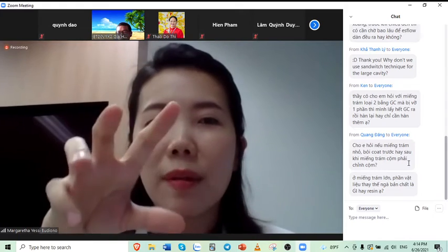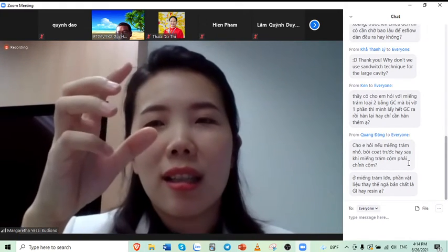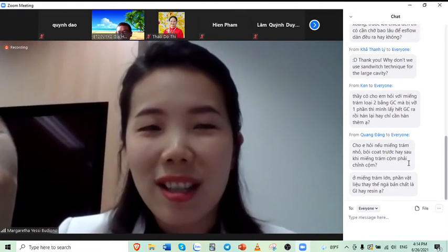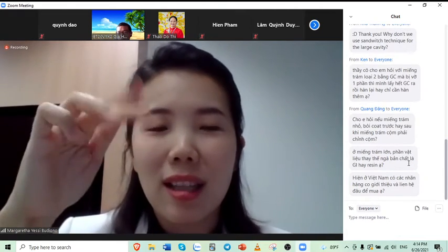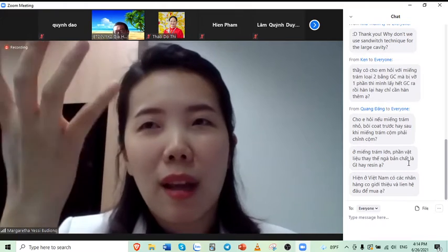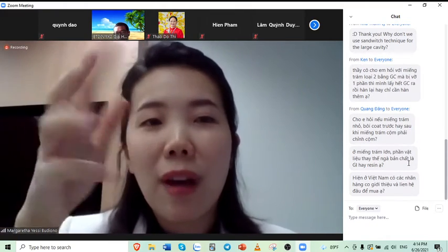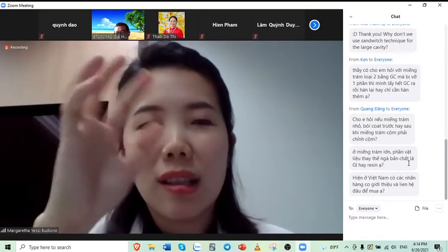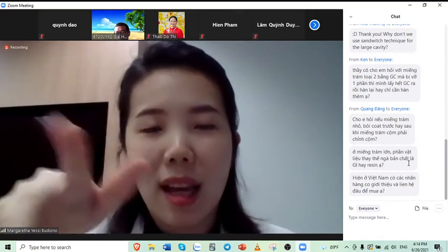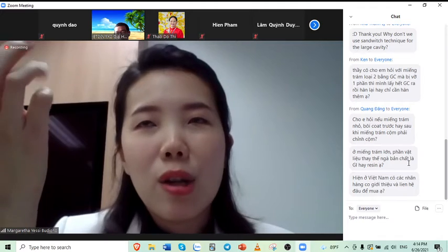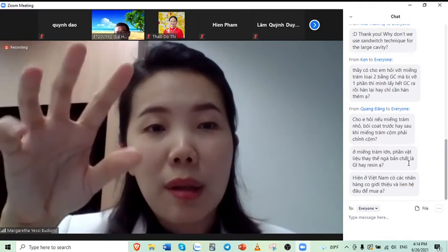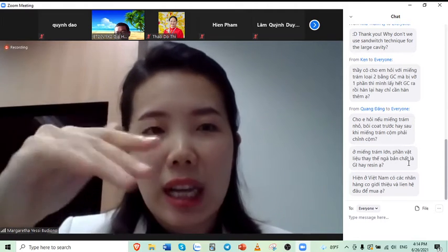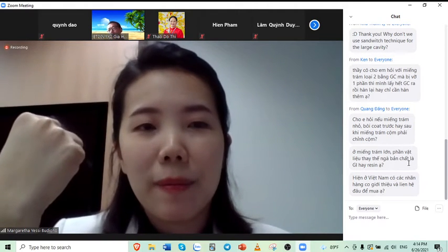Of course, the purpose of etching is generally to create a micromechanical retention between the composite and GIC. But there has been quite many research proves that it affects the bond strength actually. That's why we don't really recommend etching GIC or glass hybrid in sandwich, but instead to use a self-etching bonding agent that can bond to the glass particles inside GIC or glass hybrid.